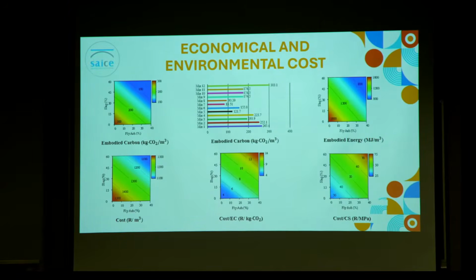In a similar way, the relationship between cost and compressive strength reveals how these materials also influence the environmental impact of the mix. Once again, the green region identifies the optimal zone where embodied carbon is reduced without a major increase in cost. Together, these findings demonstrate the importance of optimizing the proportions of fly ash and slag to yield environmentally sustainable and economically efficient concrete.